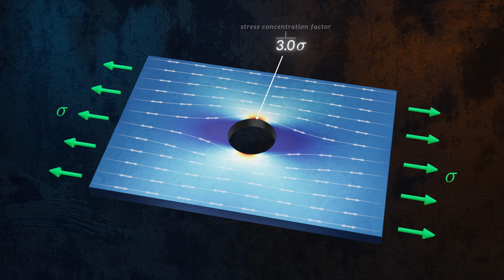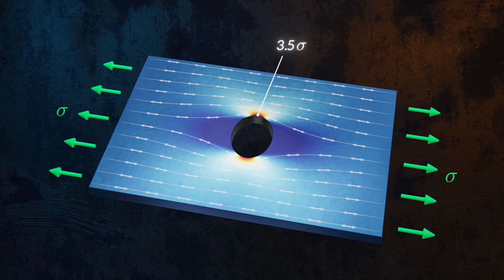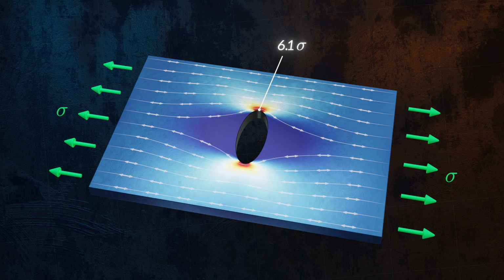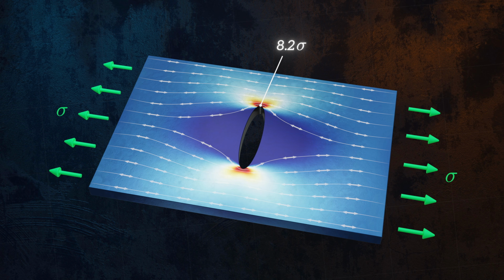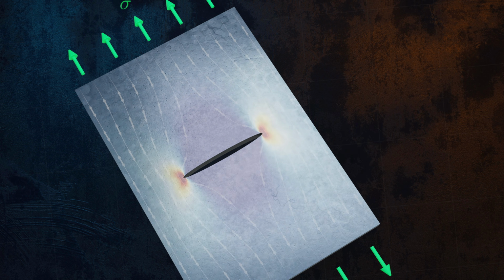If instead of a circular hole you have an elliptical one, the stress concentration increases even more. The more elongated the ellipse, the more tightly those flow lines are forced together, and the higher the local stress. This elliptical hole is essentially a crack, a sharp discontinuity where 2 surfaces have separated, leaving a region of the material unable to transmit any load, and forcing the load path around the crack tips instead. If the crack is sharp enough, the stress at its tip can reach high enough levels to permanently rearrange the bonds between atoms, or to break them altogether, which causes the crack to propagate through the material.